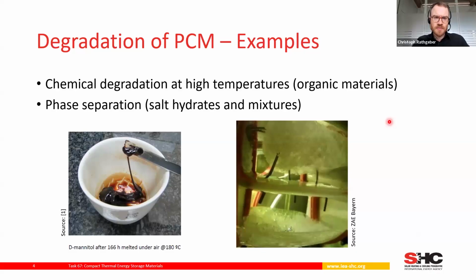Examples for the degradation of PCM. There are many more, but two very common examples are, first, for organic materials, a chemical degradation at higher temperatures. You see the picture on the left here. It's a sugar alcohol, mannitol, that was exposed to higher temperatures in the liquid phase under air as atmosphere, and you see something like a browning of sugar, which is not wanted if it's applied as a PCM.